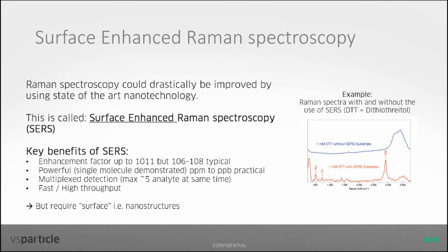So to even improve Raman spectroscopy, because it can be improved, people have been developing Surface Enhanced Raman Spectroscopy substrates. By using state-of-the-art nanotechnology to fabricate nanostructured layers, you are able to drastically enhance the Raman scattering, so the creation of this fingerprinting process. If you look to the right, I have one example where you see a Raman spectra, the blue line, without this SERS substrate, this Surface Enhanced capability. So you see almost no peaks. But then if you do the same measurement with a SERS substrate, you see a drastic enhancement of all the peaks, giving you the capability to really detect that we are working with DTT in this case.